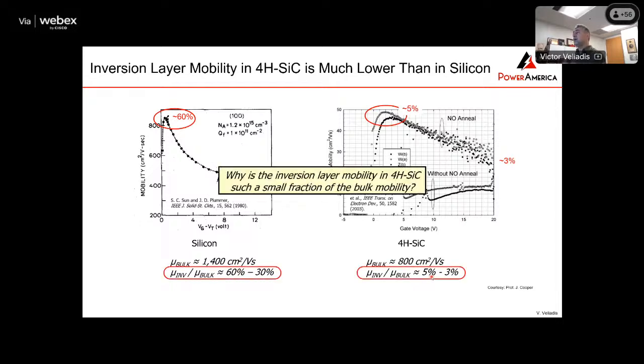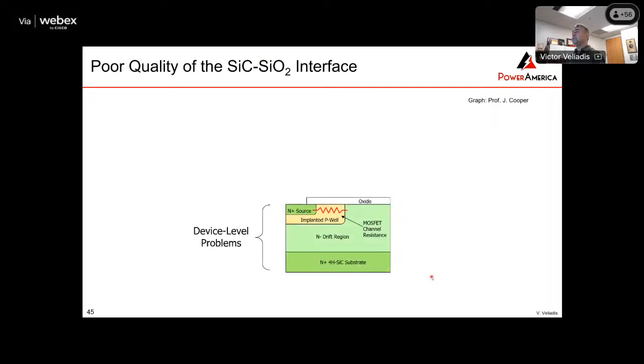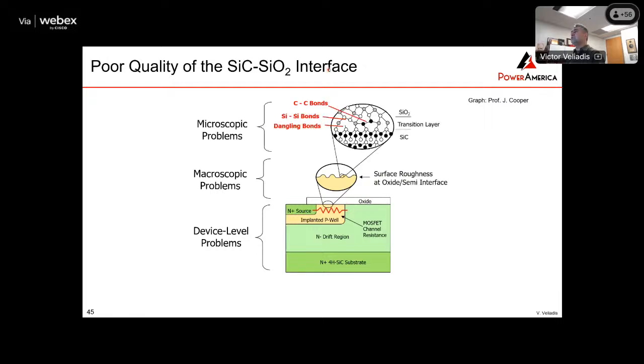So the question is, why is the inversion mobility in silicon carbide so poor? The answer is because you have a very poor quality silicon carbide oxide interface. It's got a lot of surface roughness, which is not the biggest of problems, and that's something that we're treating well now. We can basically reduce the roughness, but then you have all these carbon to carbon, silicon to silicon dangling bonds that create traps. So you have a lot of traps in the silicon carbide oxide interface, and that degrades the mobility and causes threshold voltage instability.